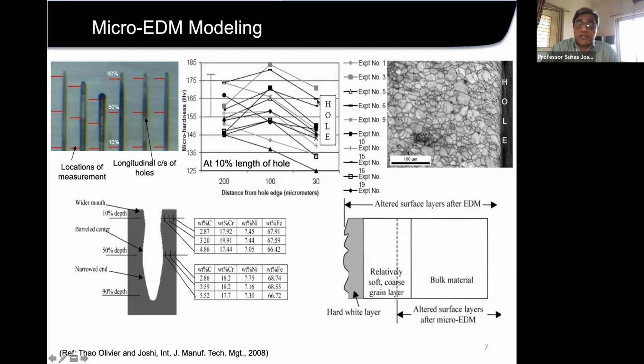We took machining parameters which required each hole to take a very long time, and some people say that since you used more time, you got no white layer. We got only a small annealed zone around the holes. But I think even there is a small bending of the grains along the hole surfaces, and that is primarily because of the polishing. Otherwise, we don't find much difference in these holes. That's what we found.